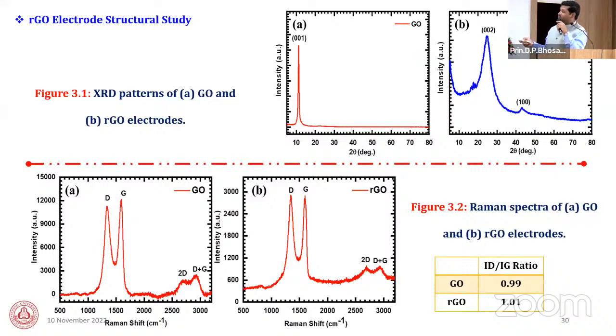This is the structural study of this RGO electrode. In this figure shows the peak position confirms the prepared material is GO, graphene oxide, and this peak positions also confirms the GO is successfully reduced using hydrothermal method, and this peaks confirms the RGO material. Also, the Raman study confirms in this peak D and G band is different and G is graphite. So the GO solution D band is less as compared to graphite because of the less defects are observed in the graphene oxide. But in the case of RGO, D band is increased because the defects are increased. That's why the D band is also increased. And the 2D and G plus D bands confirm the prepared materials, both GO and RGO, are multi-layered and nanosheet-like structure.